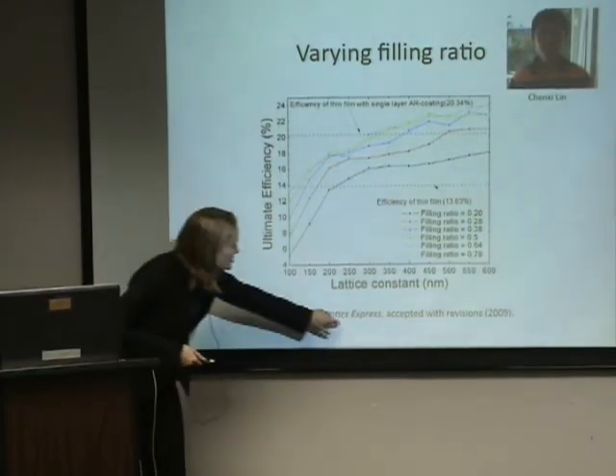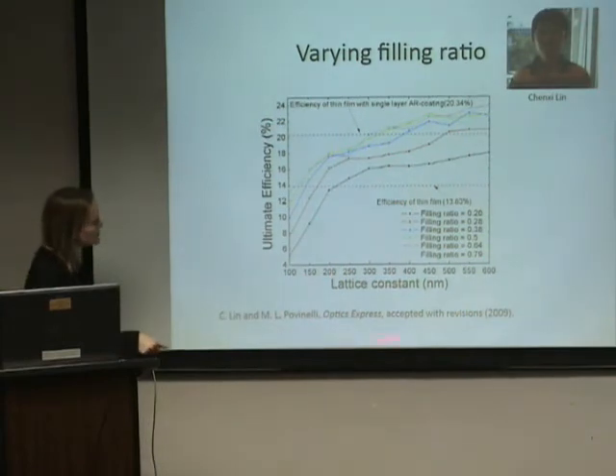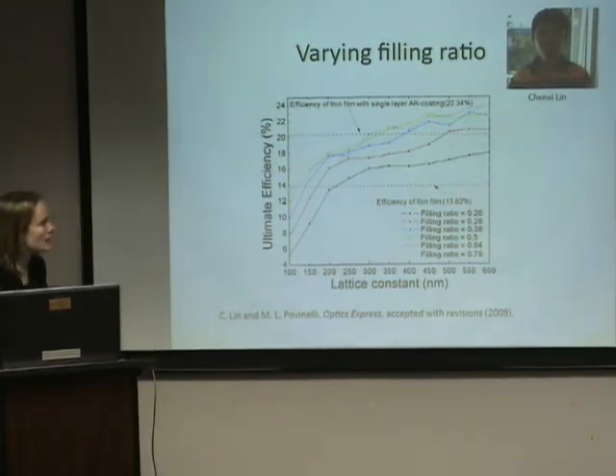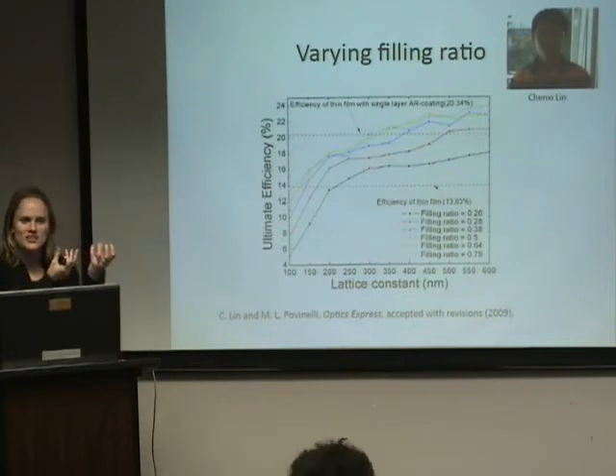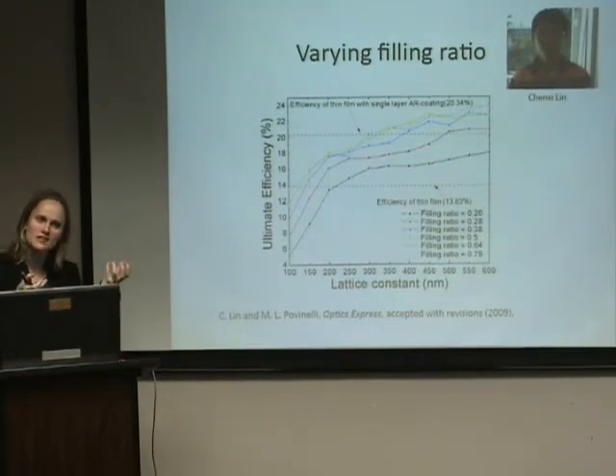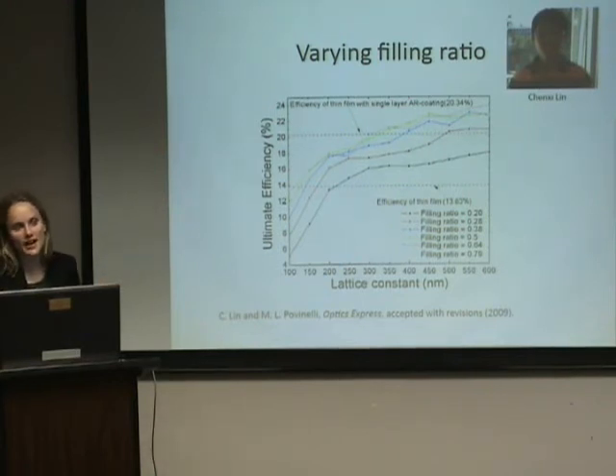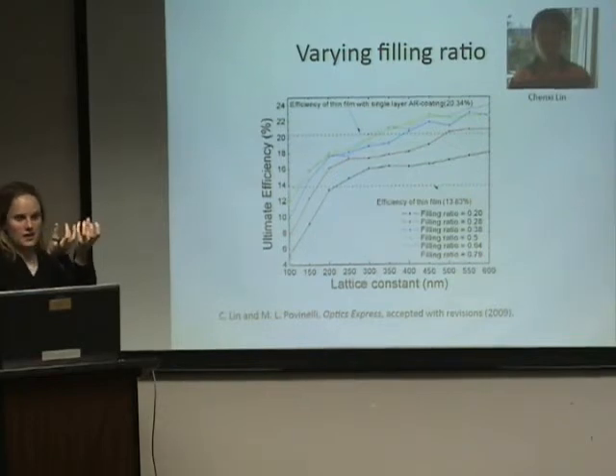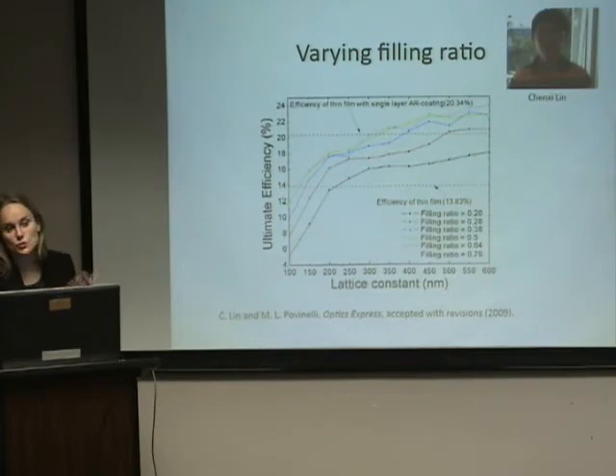Oh, this is now published. That's wrong. OK. So this is my student's work that just came out. Chenshi is a PhD student in electrical engineering. And it's a kind of neat, non-intuitive result, saying take a thing that's porous. It's a bunch of wires. It's not solid. It actually absorbs more than a solid film. And intuitively, the reason for this is that because this reflects less off the top surface, you can actually do better. You get more light in, and then you get more absorption.